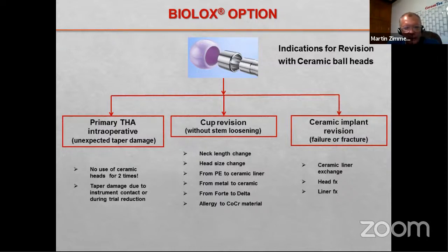If you have damage on the surface of the taper, you create locally a kind of scratch. This is strongly recommended against using a ceramic ball head, because locally you have an increase of stress, which can strongly increase the risk of fracture of the ceramic ball head. So this is always recommended in case something like this occurs during surgery.